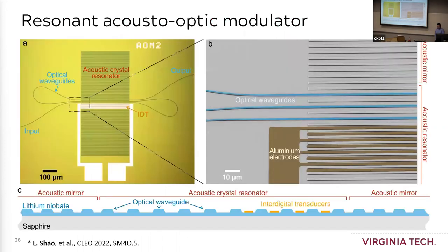So, briefly introducing how we make this thing: we link the optical domain and the acoustic domain by co-designing the structure so that it supports both acoustic waves and optical light. The way we do it is like this. The lines among those waveguides shown here are actually optical waveguides, and optical light can propagate through each one of them. But if you look in the vertical direction, those structures form an acoustic crystal, or phononic crystal.